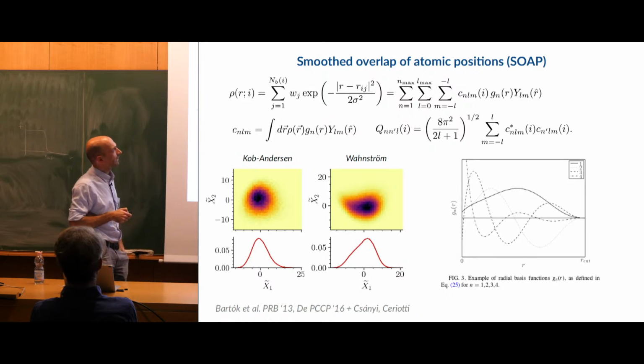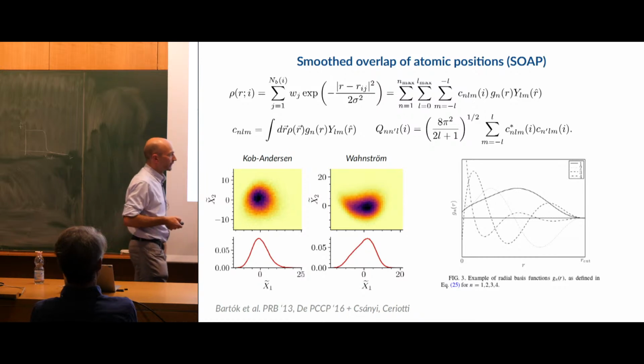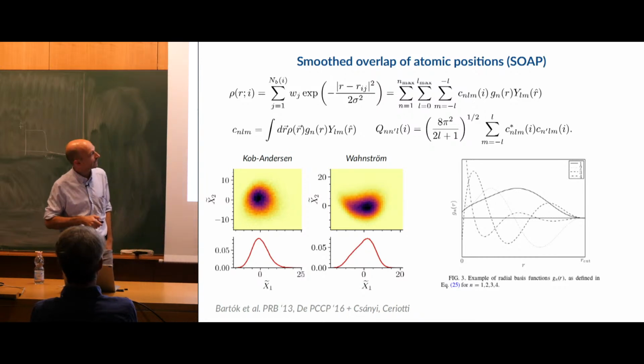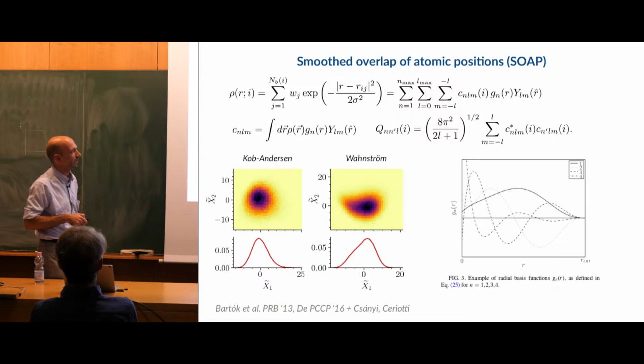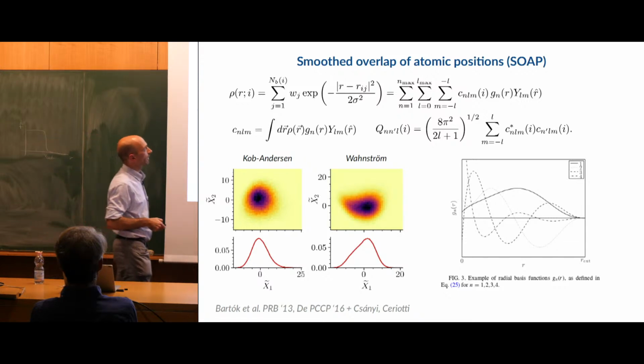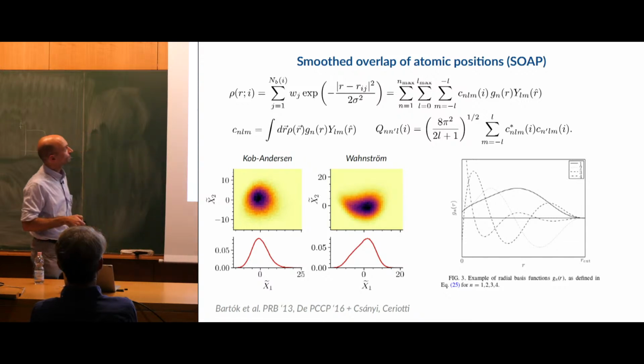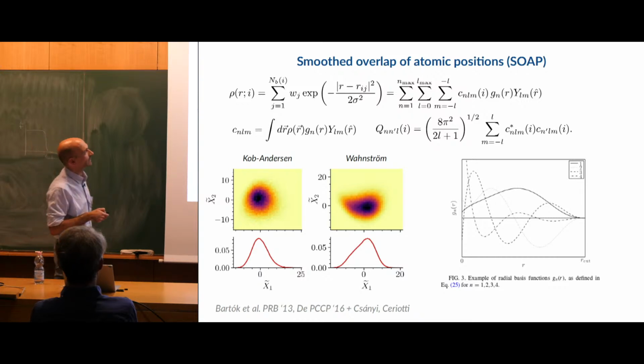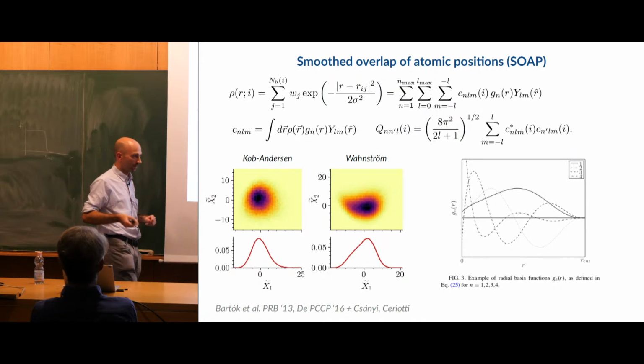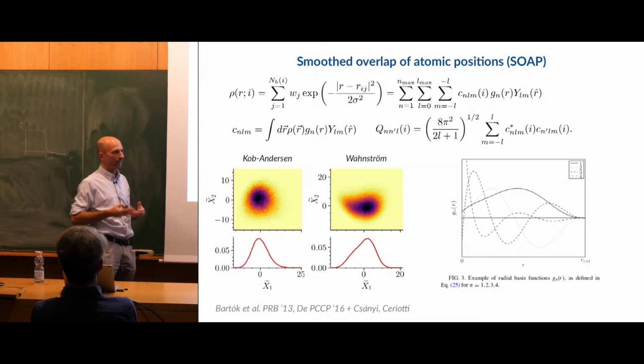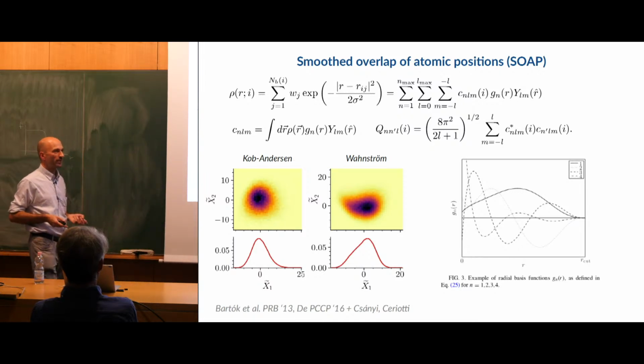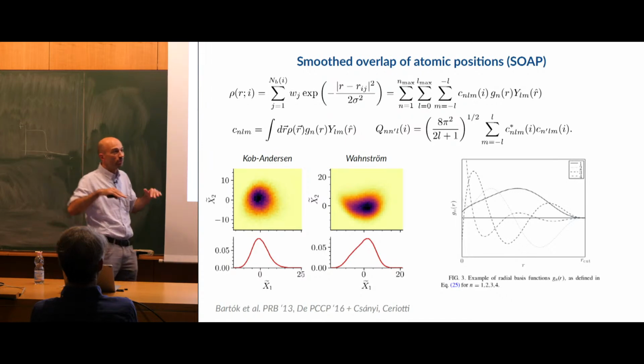So you can choose many different shapes for this radial basis, and here we simply follow the original suggestion by Csányi, which is to use this kind of sum of polynomials. And this is our radial basis. Then you construct again rotational invariants, and keep in mind here you have n, n prime, l, so you have many more numbers. So you typically get 200, 300 parameters to play with and to reduce dimensionally. And this is what we do.